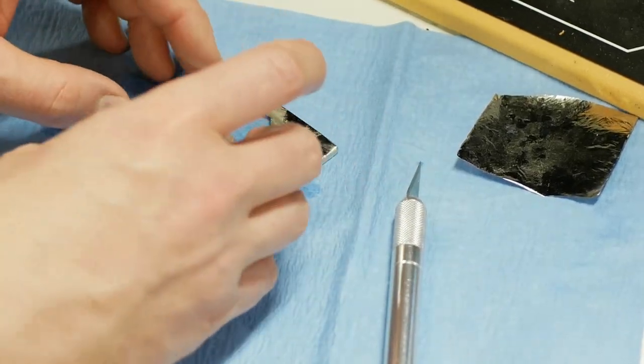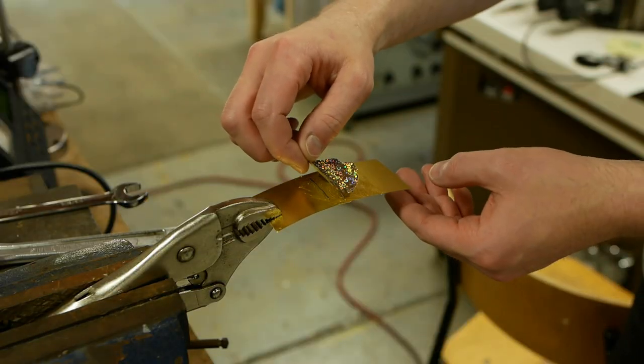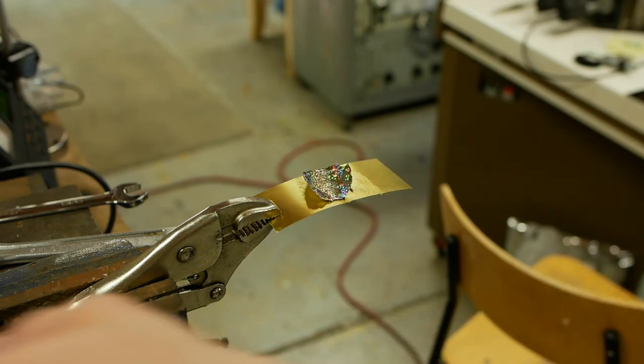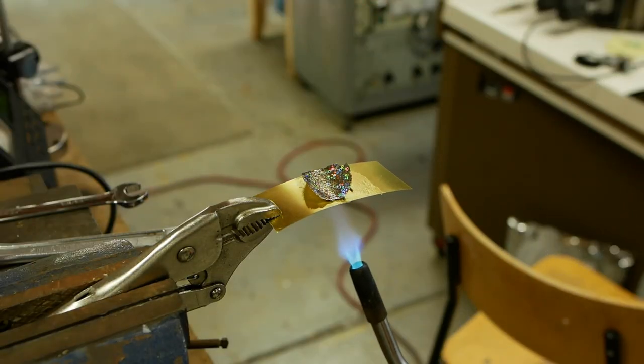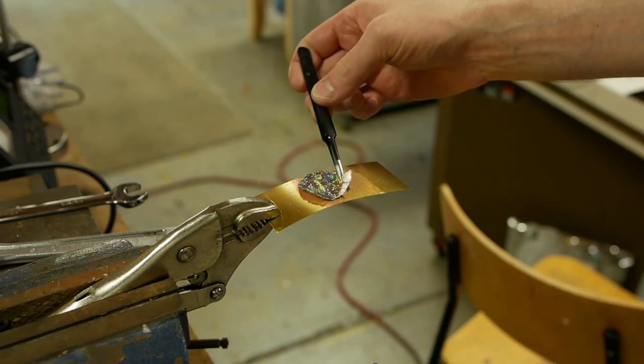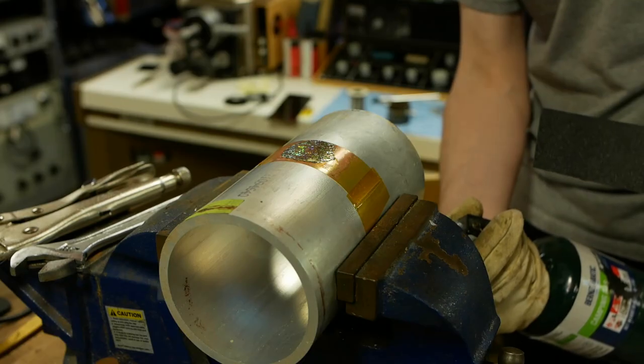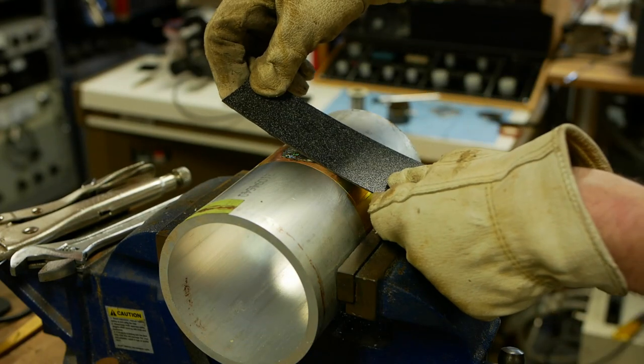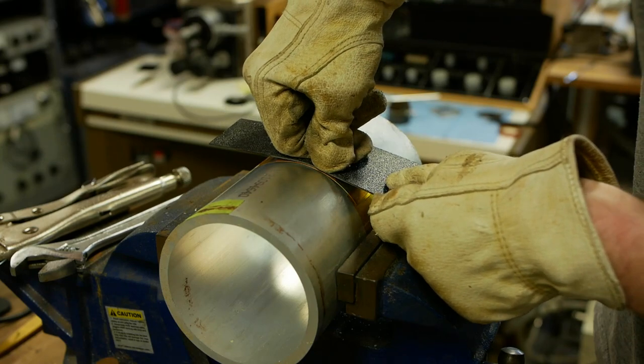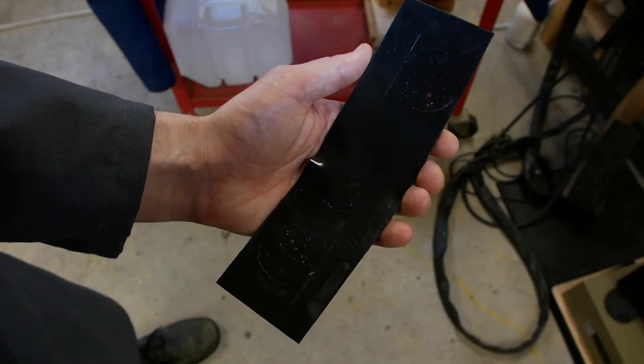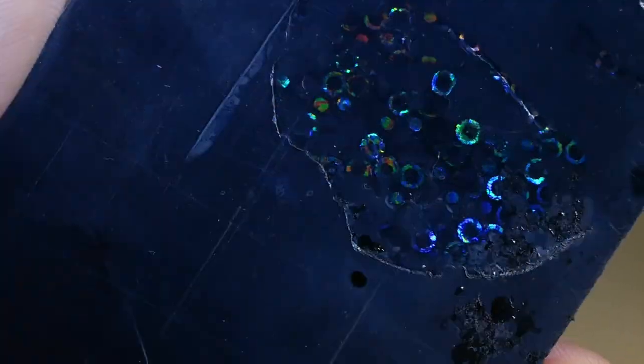It's still very thin, though. So then what we do is add that onto another piece of metal. So now we've got very thin silver, thin nickel, and then thicker brass. And the way I decided to attach it was just with soft solder, lead-based solder. And this worked better than I thought, but it also kind of wrinkled the foil a bit, and it's kind of distorted. But much to my amazement, putting it all together on this aluminum pipe, heating it up, and then pressing plastic with basically just hand pressure on there actually produced a pretty good result. So now we have basically a hot stamping die, and you can stamp holograms onto any kind of plastic you want, or at least plastic that can melt lower than the metal die will. Pretty cool.